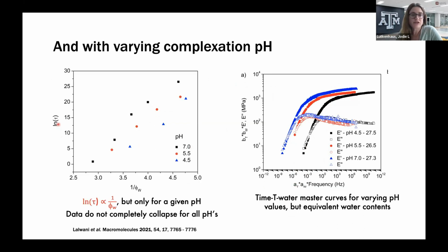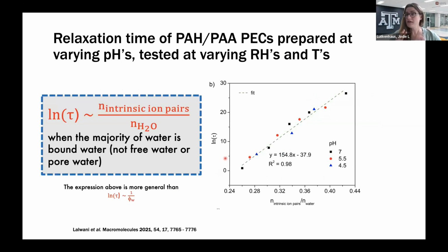Now, if we try to plot the natural log of the relaxation time with 1 over the volume fraction of water within a single pH, yeah, it's linear, but they don't collapse onto the same curve. So it means that within that pH, the relationship holds, but it's not general to the whole system. However, if we take the same data but plot it against the ratio of intrinsic ion pairs to water, then it collapses into a single curve with a very good linear fit. And again, no adjustable parameters. So this result indicates that the natural log of the relaxation time of a polyelectrolyte complex is related to the ratio of intrinsic ion pairs to water.